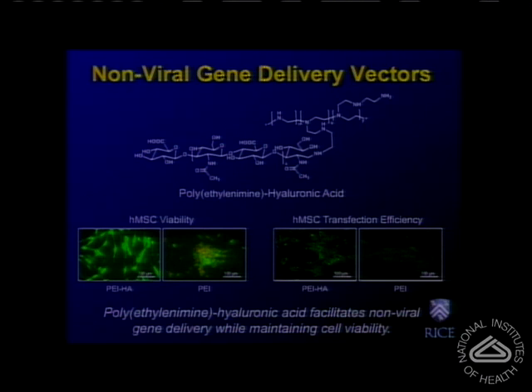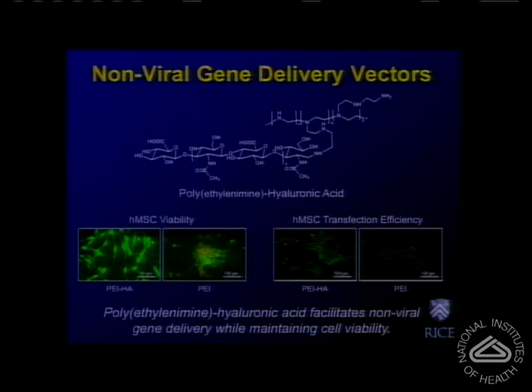It's a conjugate of polyethylenimine together with hyaluronic acid. Polyethylenimine is the gold standard of a polymeric non-viral vector. However, it's a material that exhibits high cytotoxicity, and many people relate the high cytotoxicity to the high transfection efficiency. The reason that we conjugated this hyaluronic acid to the polyethylenimine is to use a mechanism for targeting for these conjugates, but also in an effort to reduce the cytotoxicity of the material.